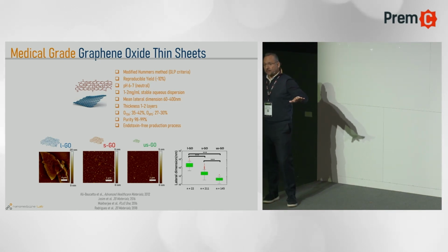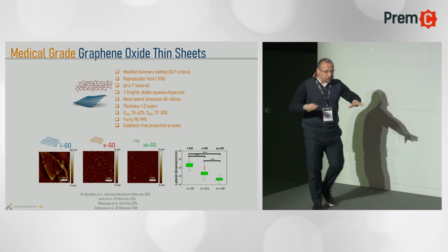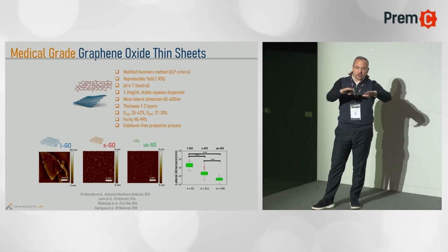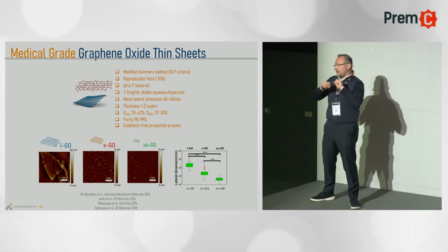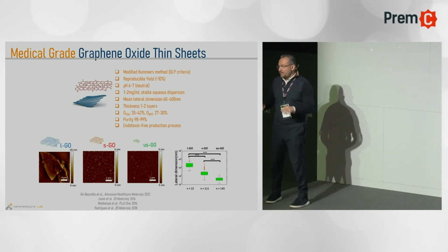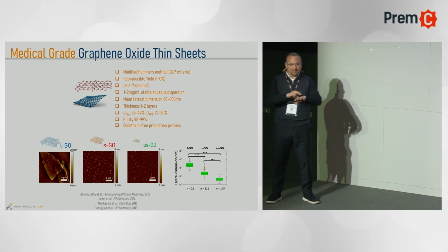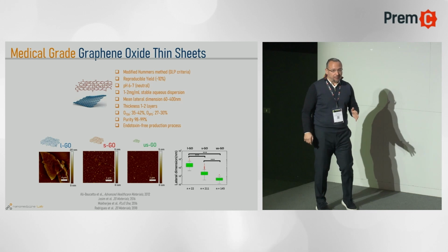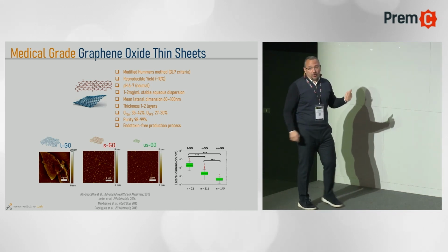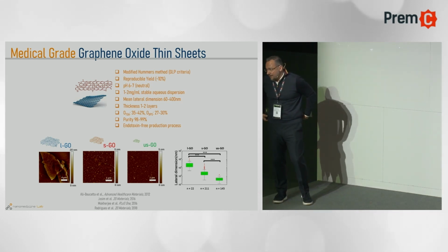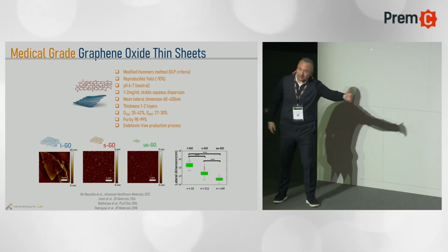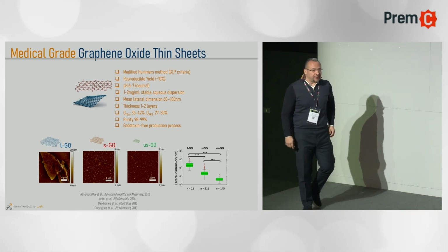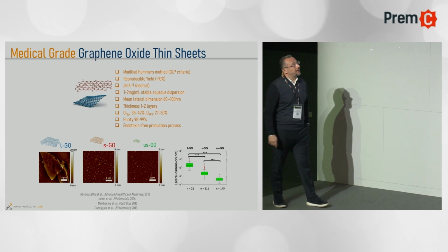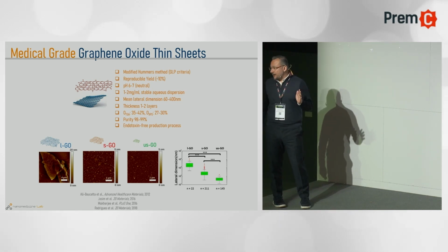So we have almost 1 order of magnitude difference between the 3 types of materials. Everything else the same. The oxygen groups on the surface of these materials, of these sheets, are the same. The thickness of the material is the same. The fabrication is the same. Impurities are the same. Exactly the same. Also very important to note is the lack of endotoxin impurities. If you have endotoxin impurities in your material, you will carry them through in whatever biological studies you decide to undertake. So that's another thing we were very, very meticulous about.